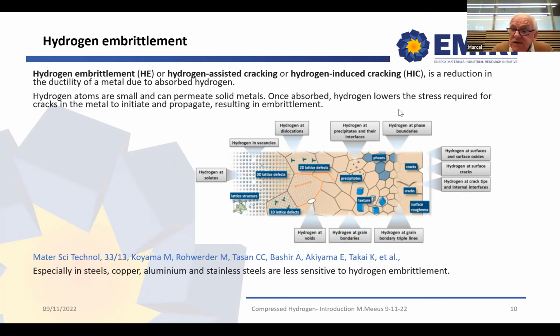Hydrogen can diffuse into the metal, react at the grain boundaries, in the voids, and in the dislocations in the metal structure as a whole. Steels are quite prone to hydrogen embrittlement. Copper, aluminum, and stainless steels are less sensitive to hydrogen embrittlement.